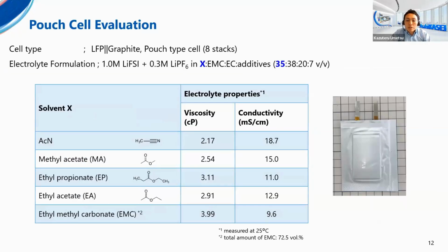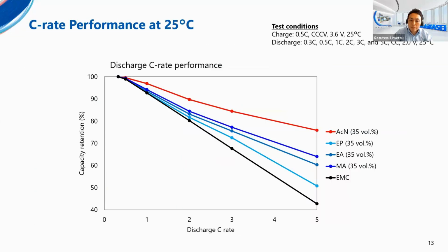So next, cell evaluations were carried out with the LFP graphite system using the electrolytes evaluated on the last page. 8 stacked pouch cells were assembled, and its photo is here. First, here are the results of the C-rate performance at 25 degrees C. After charging at 3.6 volt, cells were discharged at 0.3 C, 0.5 C, 1 C, 2 C, 3 C, and 5 C to 2.0 volt.